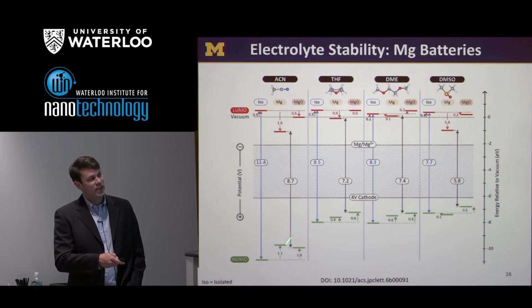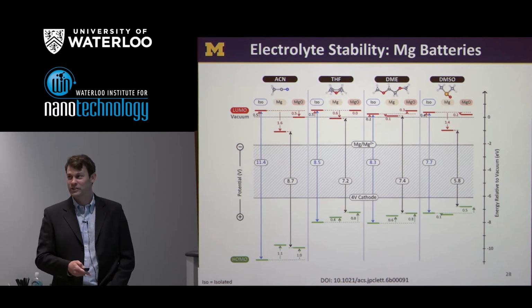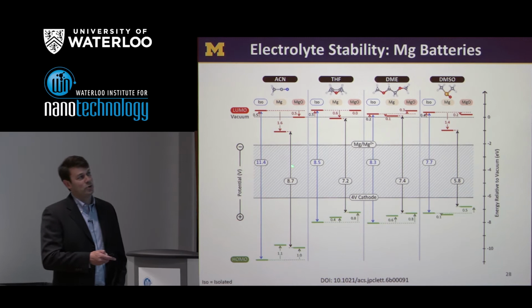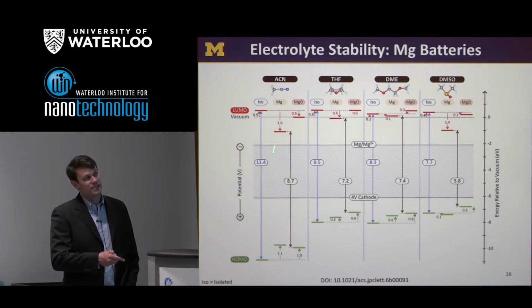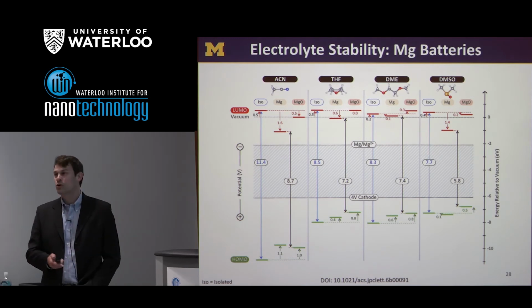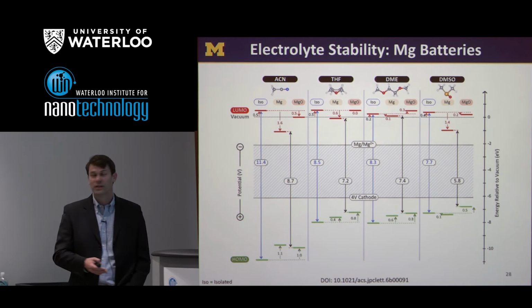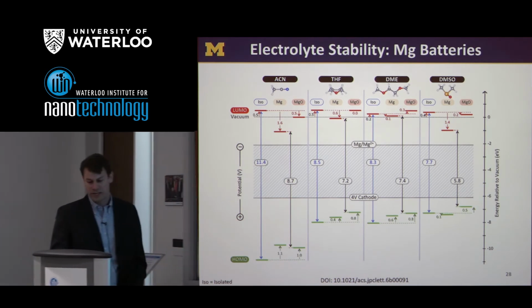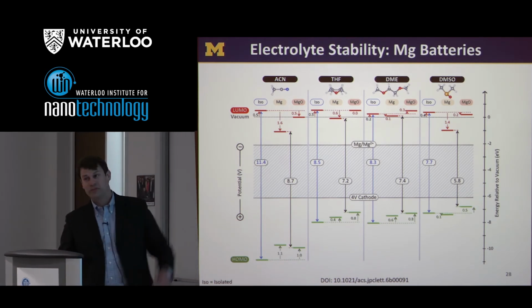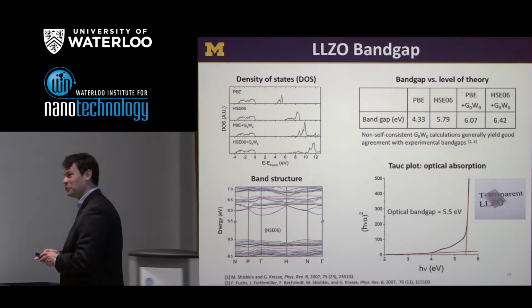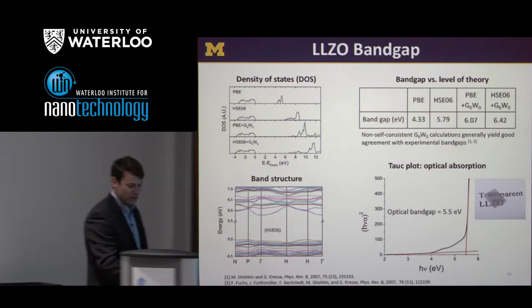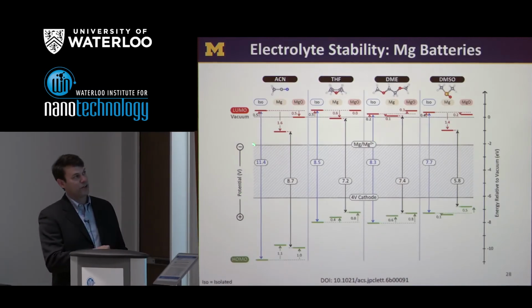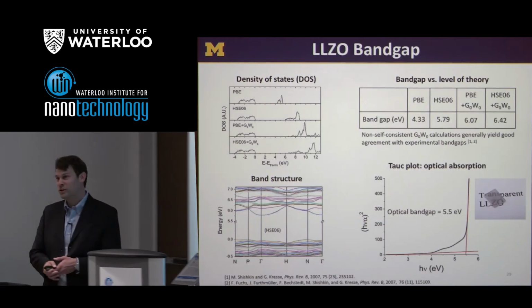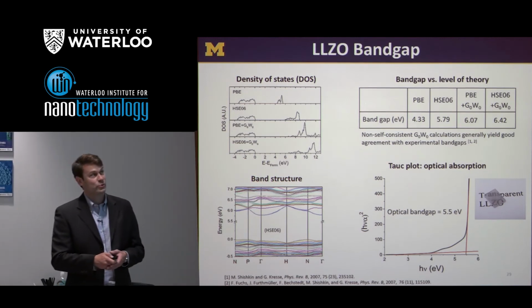Something similar can be examined with respect to the HOMO by looking at interactions with a model cathode material. In this case, we just use magnesium oxide. And so the upshot is that you can see that the isolated materials have rather large gaps, but in some cases they shrink by up to, say, a quarter of their total size due to these renormalizations at interfaces with electrodes. So we would love to do this with solids. We can't yet include these interfacial effects. And so what we're doing right now is looking at the isolated limit of solids and again trying to position those HOMO and LUMO levels, or CBM and VBM, in an absolute sense.